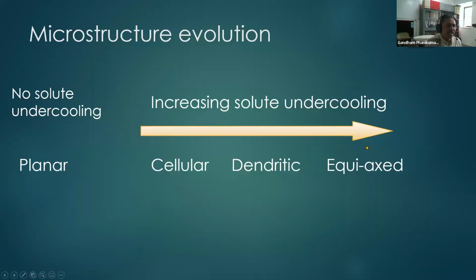So what happens as you increase the undercooling or the solutal concentration or the driving force is that the microstructure will change from planar to cellular to dendritic and equiaxed. We are very interested in these transitions because if you want to print a single crystal through additive manufacturing, we must have our parameters such that planar growth is encouraged. And if you are interested in a microstructure that is resilient to crack propagation, it should be very tough, then you may want to encourage equiaxed growth. So understanding these transitions helps us determine the conditions under which such microstructures will form.